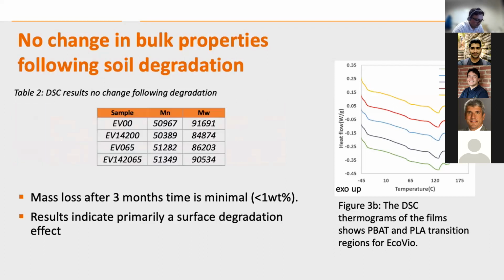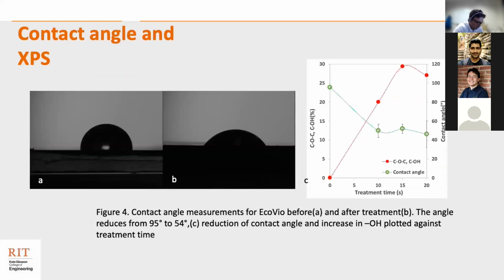Another thing that confirmed no change in bulk properties was the average molecular weight determined using a GPC, or gel permeation chromatography. As we can see, the average molecular weight revolves around 50,000, which means we are not changing any bulk properties of these films. Now that we have established that we are not changing the bulk characteristics of these films, we needed to confirm the changes we are making on the surface.